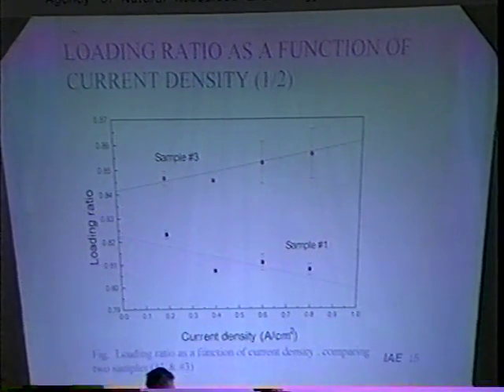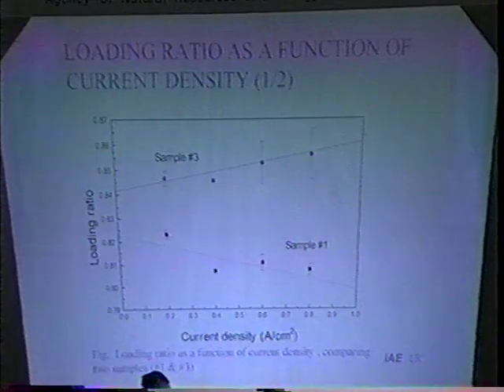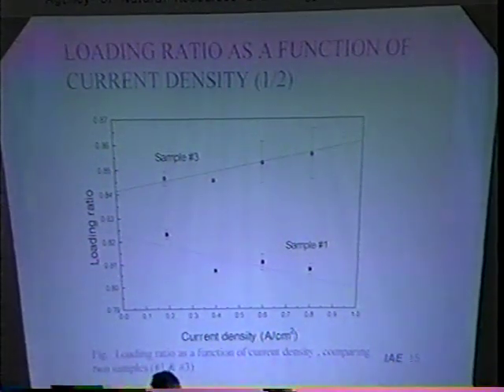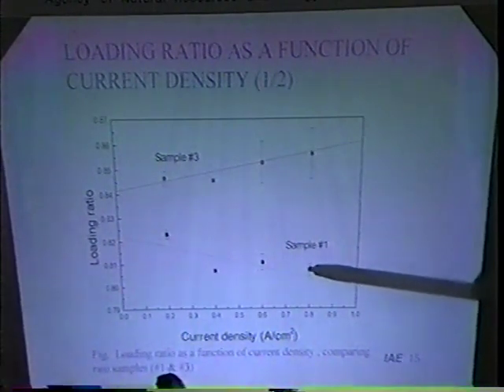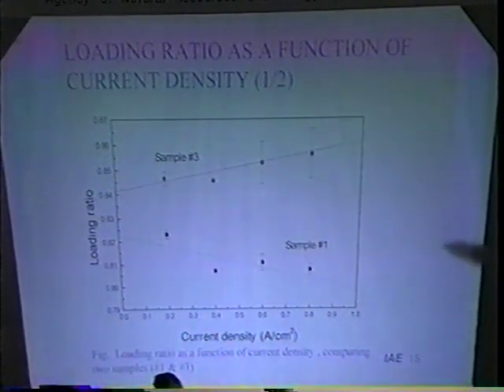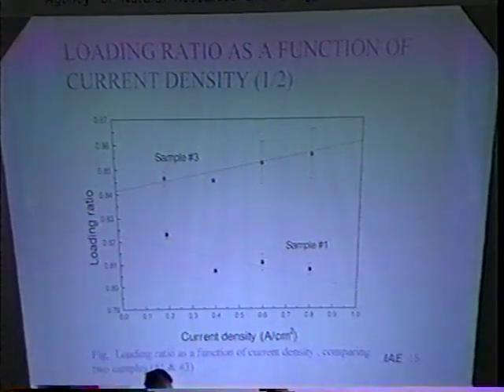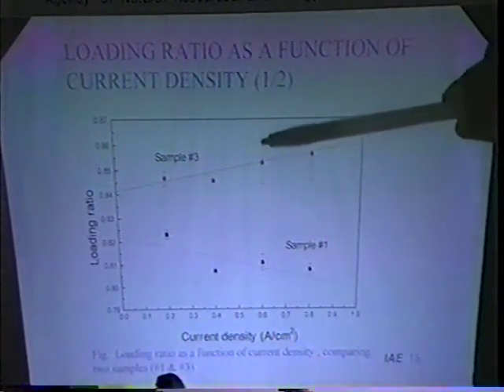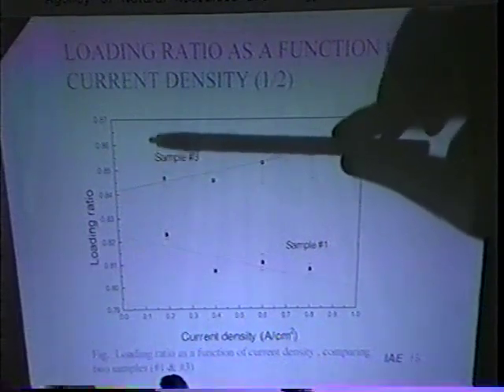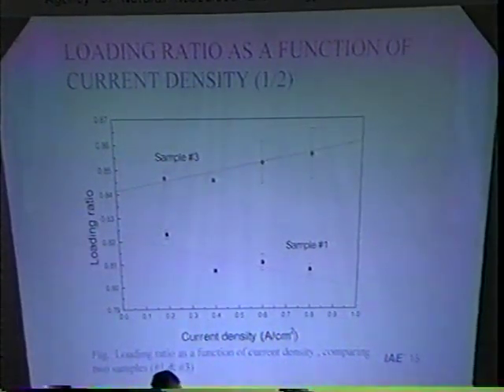This figure shows the loading ratio as a function of current density comparing two samples. The data from 2 weeks after the start of electrolysis and in stable equilibrium were used to calculate this relationship. The D/Pd ratio of sample number 1 with no excess heat became lower at higher current density. On the other hand, the D/Pd of sample number 3 with excess heat increased or did not decline at high current density supply.